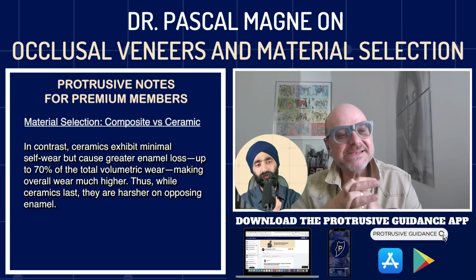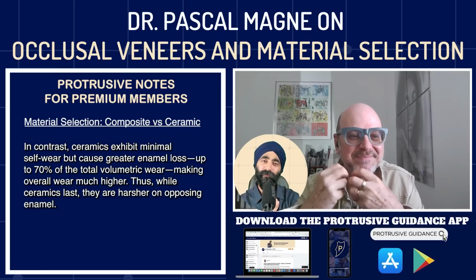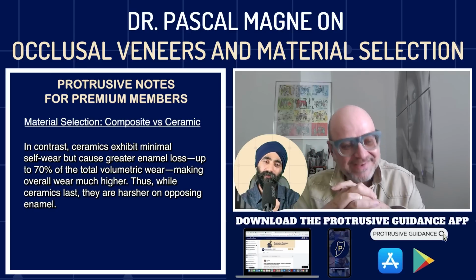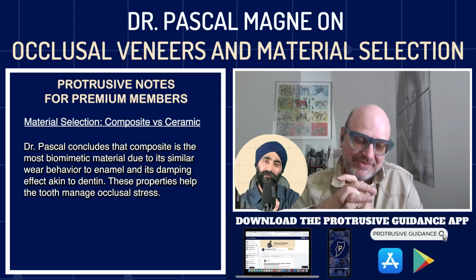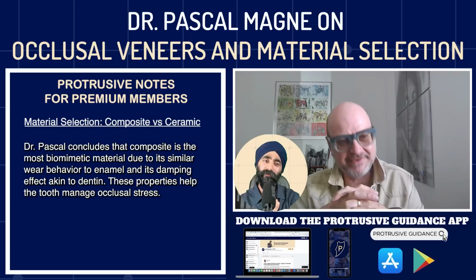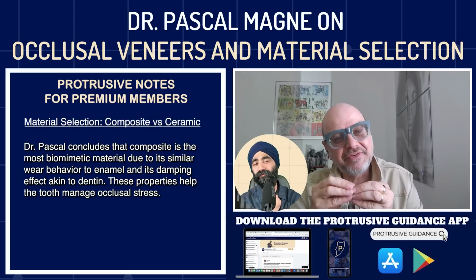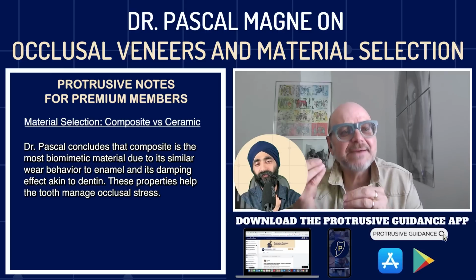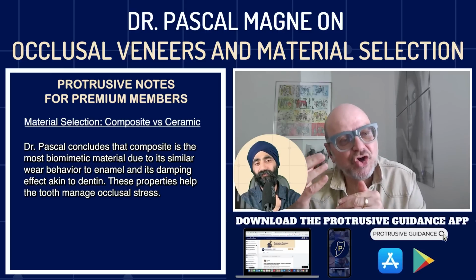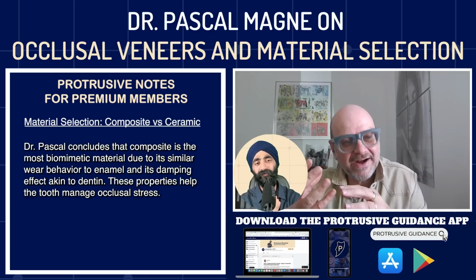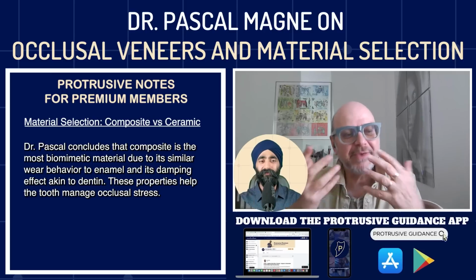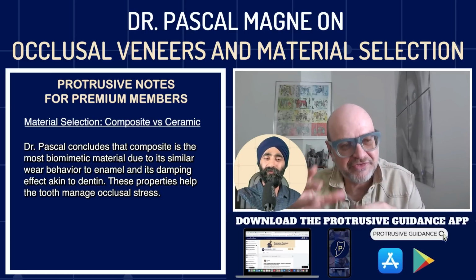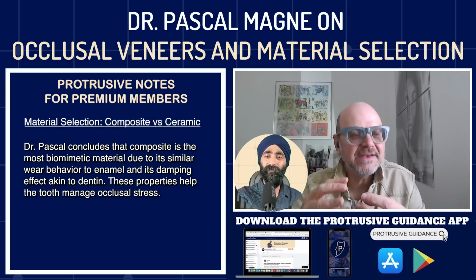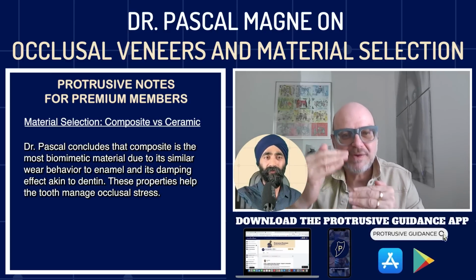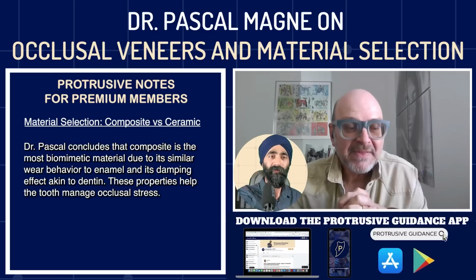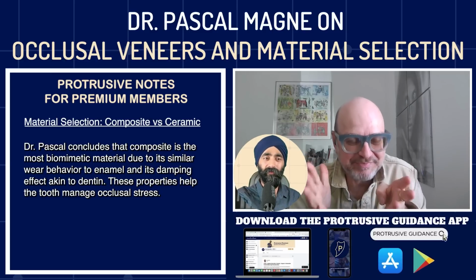So when people ask me, what is the most biomimetic material in general? I tend to say the most biomimetic material is composite resin. Why? Because composite resin has wear properties very similar to enamel, and elastic modulus, which is the damping behavior of the dentin. So wear and damping behavior. And that's what makes the tooth very unique. The enamel resists wear. The dentin is a damping structure to absorb the deformation.